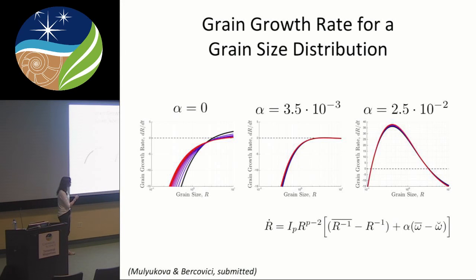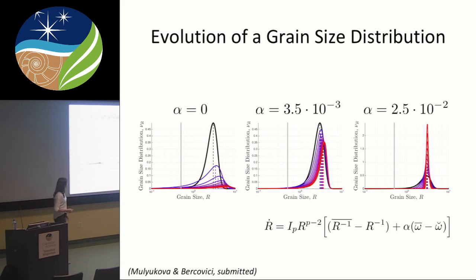For an even larger alpha, we'll have shrinking of grains that are too big because now the dislocation effect will be stronger, and so it will drive the grain growth back to where you see here would be the steady state. So the way it manifests in the grain size distribution itself, this is the case I already showed you. It's broadening and shifting to the right.